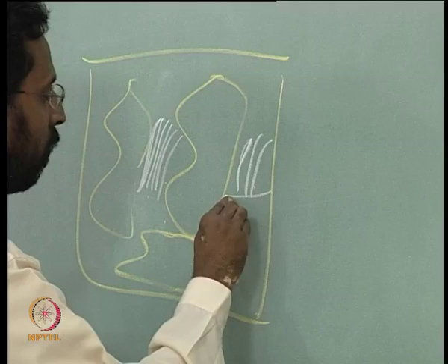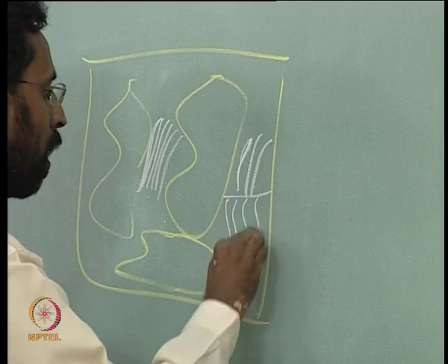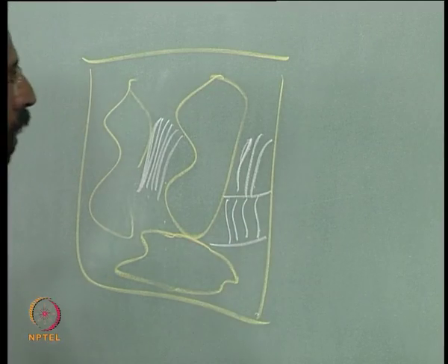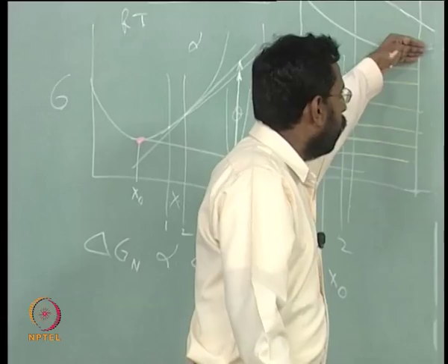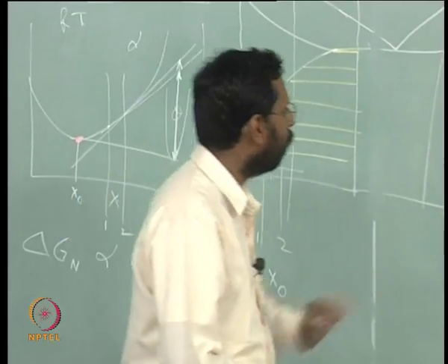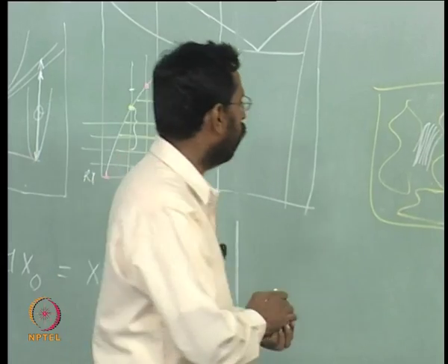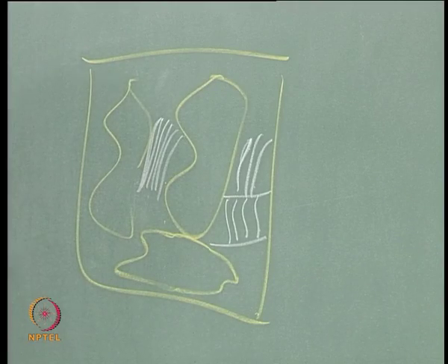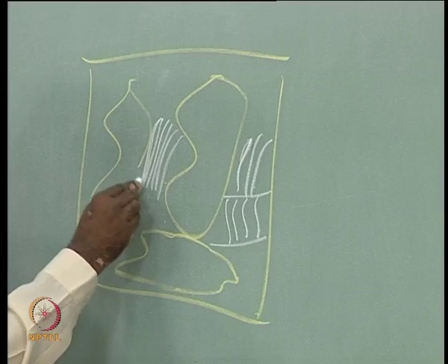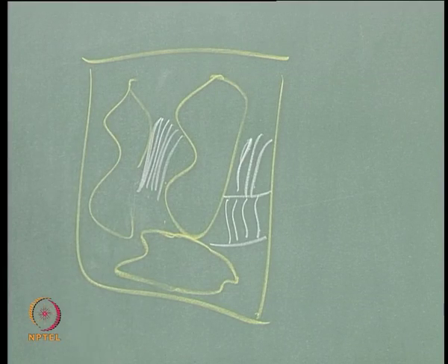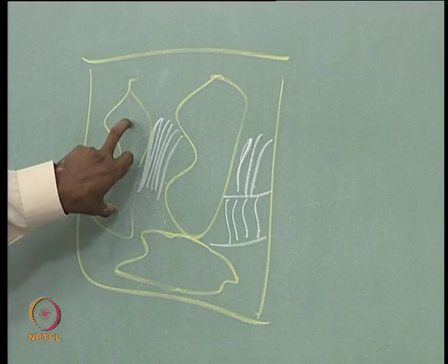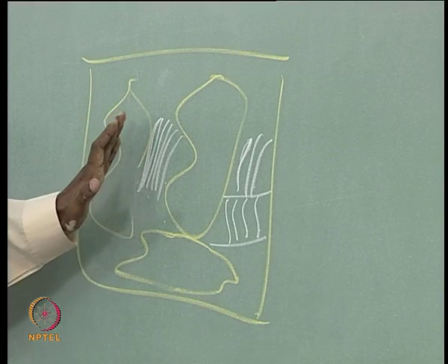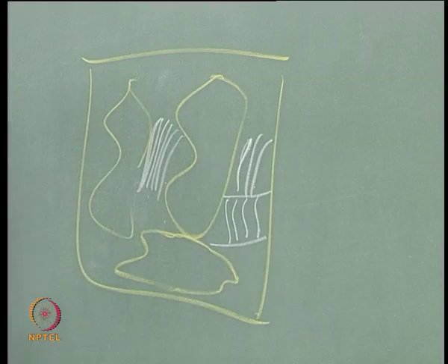there can be boundaries which are called eutectic colonies, and you will see lamellae where you have that. And after the solidification, as you further cool, if you want to look at where this forms, that extra theta phase will start forming on the theta which is already there close to the dendrites, because the excess copper is coming out of the dendrites actually.